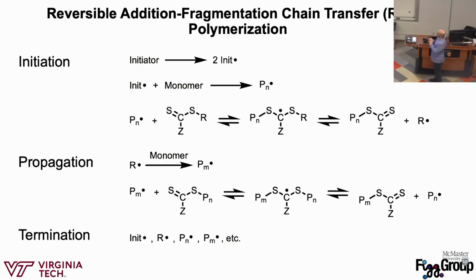RAFT starts with this conventional initiation pathway, usually. So this could be a thermal initiator like AIBN, where you heat it up and then it thermally degrades. You lose nitrogen and you can get two initiating fragments. These initiating radicals are going to react with monomer in solution to give you this prepolymer. And then this prepolymer is going to react with this. This is what we call the RAFT agent. It's a thiocarbonyl thio compound. So these are specifically designed to mediate the polymerization.